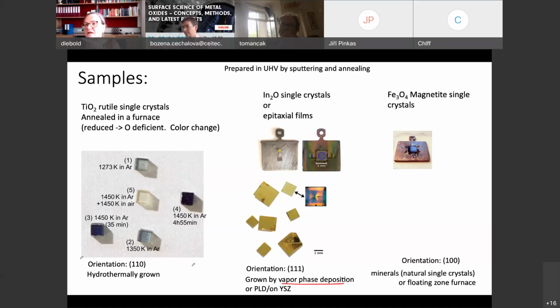TiO2, I had this question at the beginning, why are we interested in TiO2? Actually, another reason is it's really easy to handle. You can buy single crystals pretty cheap, $100 per sample or so, in any sort of orientation. They're hydrothermally grown, which is a relatively inexpensive growth method. If you buy a single crystal of TiO2, it's optically transparent. It has a 3 eV band gap. Electrons can be excited from the filled valence band to the conduction band. We treat them in ultrahigh vacuum by cleaning them, by sputtering and annealing.